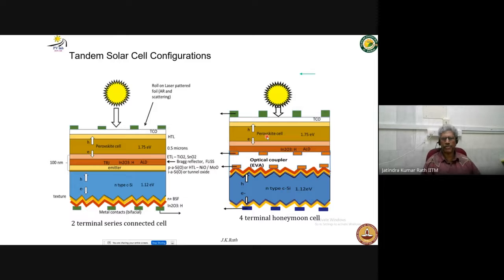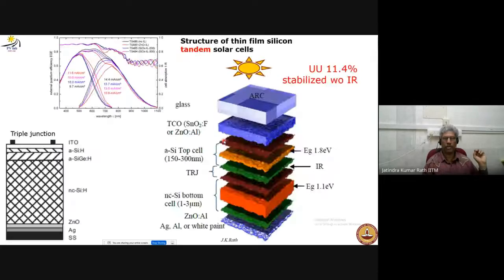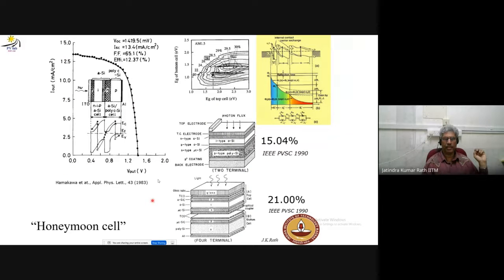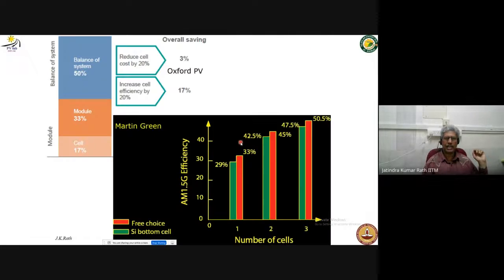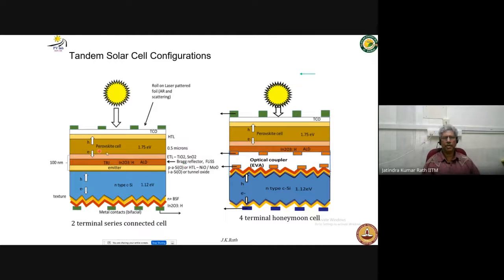So this is what the 2 types of cells are. And I told you previously the amorphous silicon top cell and crystalline silicon bottom cell didn't work. I told you before. Yeah, here. You can see here, it was only this much percent. It was not much. So now that has changed. What has changed? There's a new type of material called perovskite cell. These are all organic-inorganic type perovskite materials, such as methyl ammonium lead iodide. This has a perfect band gap, 1.75, similar to amorphous silicon. But the quality of the film, the material, is far, far better compared to amorphous silicon. There is very little defect in them. The efficiency of single junction perovskite cells has reached up to 26%.